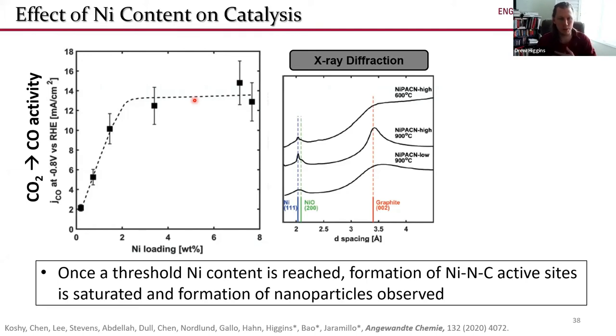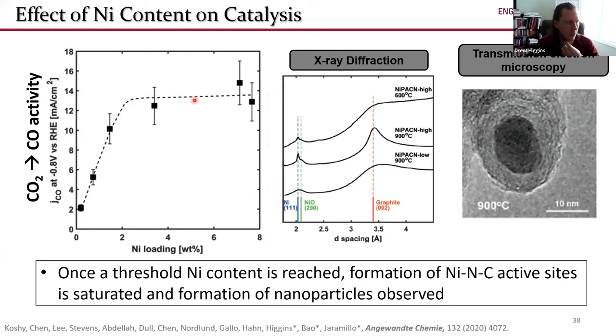None of those particles were forming, which meant our nickel content was below some sort of threshold value, after which nucleation and growth of these particles would occur. But what was interesting was that even for the catalyst that had a lot of nickel in there, the selectivity was also still fairly good towards carbon monoxide, even though we saw the formation of these nickel particles. And nickel's actually, under CO2 reduction conditions, much more selective towards reducing water into hydrogen. So we would have thought our catalytic selectivity would go way down when we had these nickel particles present in the catalyst, and we didn't see that.